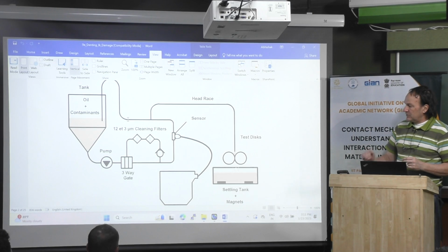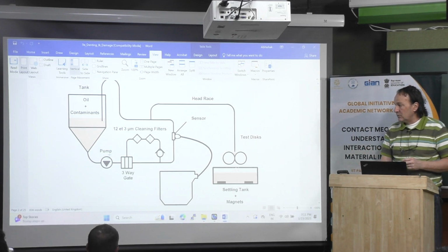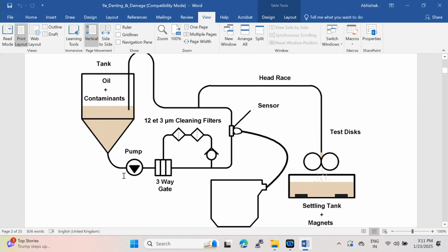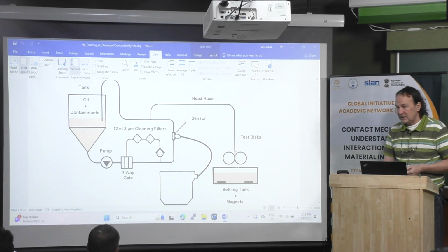And the last point about that, for the pump, you should be careful about the type of pump, not to use a gear pump, for example, because a gear pump will deform the particles. If you have metallic particles, then you should have a pump which is not a gear pump. Typically, a screw pump, for example, is a good type of pump. And then after that, we have a small, what we call here a peristaltic pump. We just take a small percentage of the flow, and you can lubricate a machine like that.